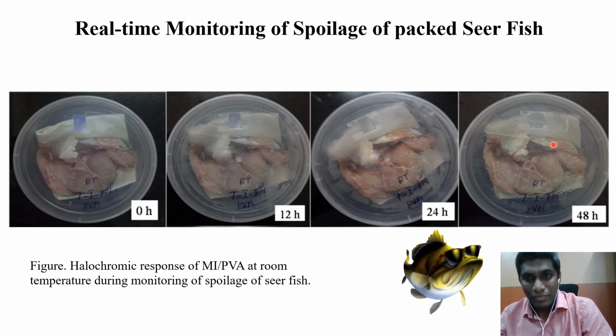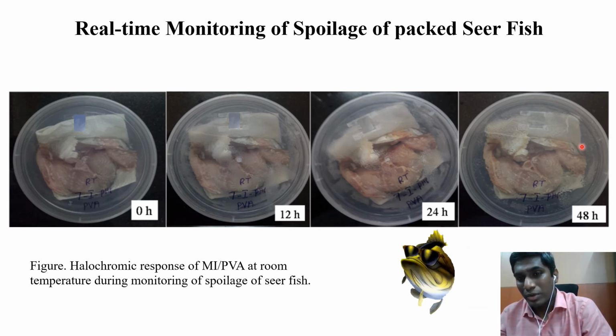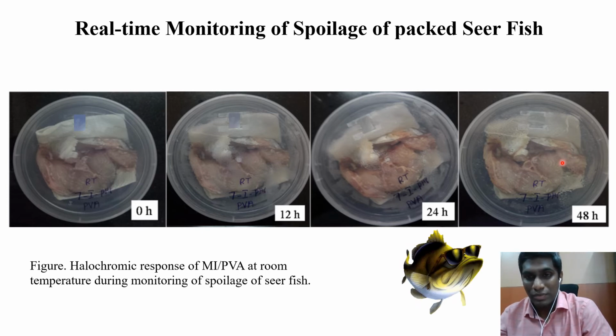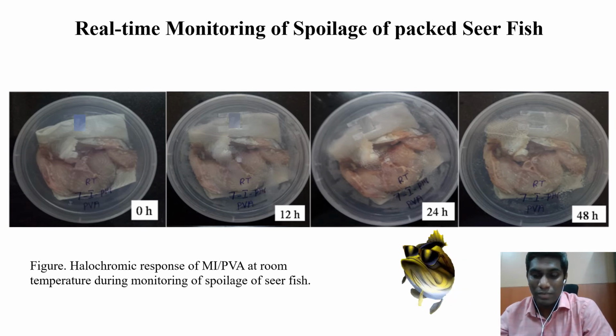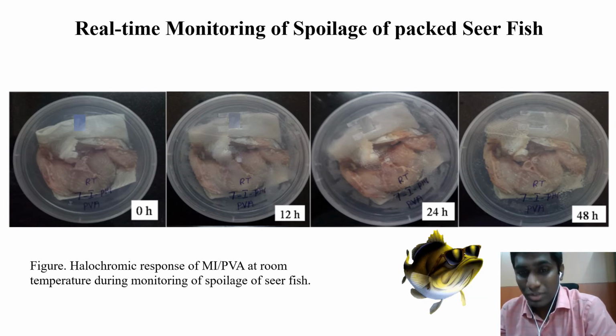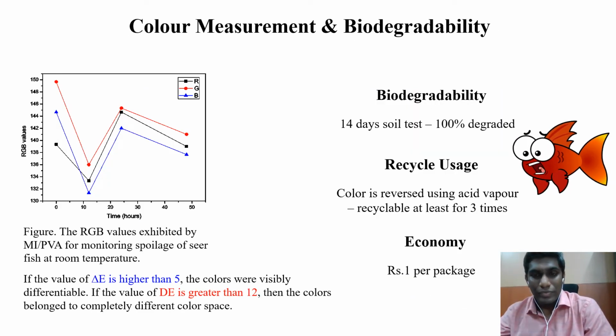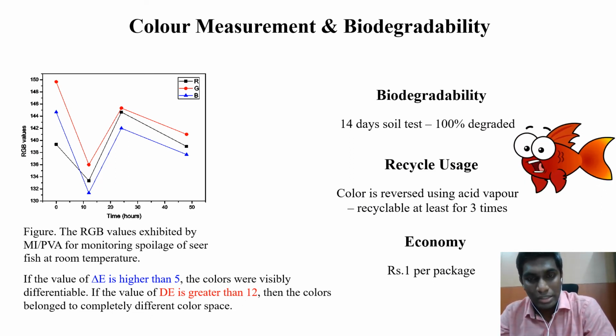At 48 hours, most of the film was completely color changed, and we also observed the interference of the moisture, because when fish spoils, it not only releases the volatile amine, it also releases large quantities of moisture. We performed similar experiments at refrigerated condition and also in frozen condition, and the color changes were similar.